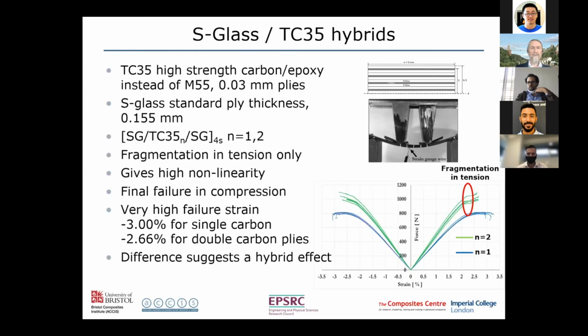So then we change the fiber, instead of having an M55 high modulus fiber, which has a relatively low strain to failure, we put a TC35 high strength carbon epoxy instead. So the setup is the same: S-glass standard ply thickness with one or two of these high strength carbon thin plies sandwiched between them and loaded in 4-point bending. So again, we see a high nonlinearity, but this time we only get fragmentation in tension. Because of the much higher failure strain of this TC35 carbon fibre, we don't see any fragmentation in compression.